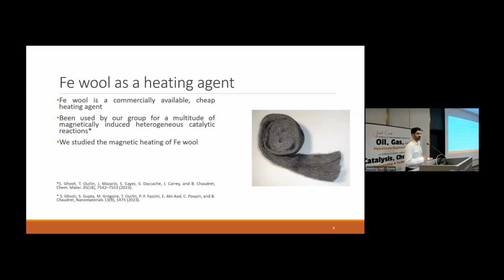So it's heating under induction waves. It's really good. And we've been using it in our group, so in the University of Toulouse, to do multiple magnetically induced reactions, such as the methanation of CO2, methanation of CO, the reverse water gas shift reaction, some other hydrogenation reactions. But in order to optimize its use and to be able to do some modelization afterwards for some reactions and reactors, we had to do a little bit of a deep dive into the mechanisms that are used in the heating of iron.